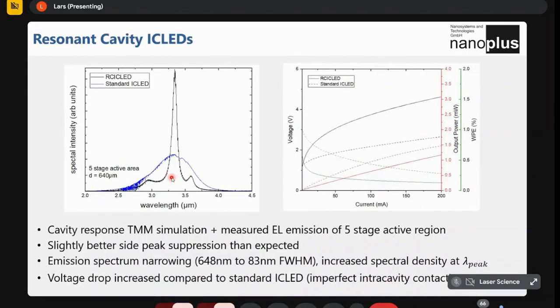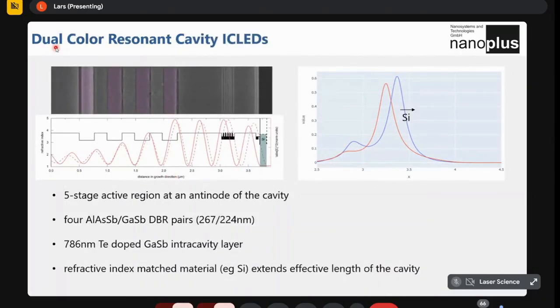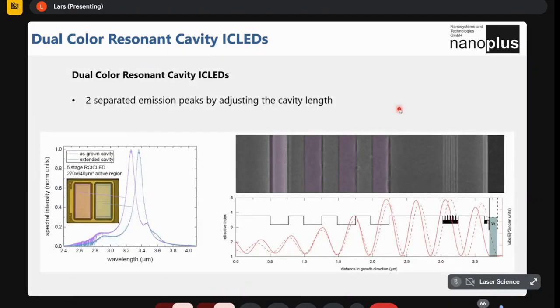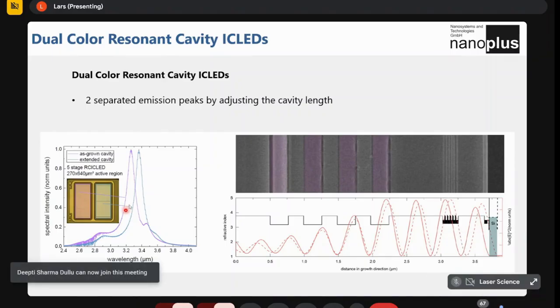And those are also tunable or dual color, as we call it. So everything from here to the left is the same like in the resonant cavity LED. And now you take a little silicon growth on top of that LED, which makes the cavity longer. And if the cavity is longer, then the wavelength is shifting, of course, to a slightly different wavelength. And as you can see in this slide here, this is 2 color LEDs. They are from the same growing process. One of them, this one here, has a little silicon on top, and the other one doesn't have that silicon on top. And you can switch between them. And so you can see the light is switching about something like 100 nanometers away to a different wavelength.